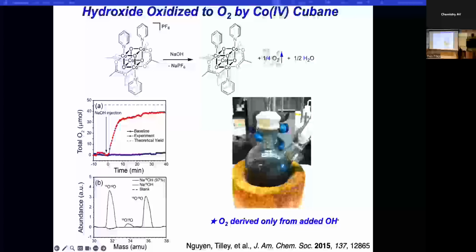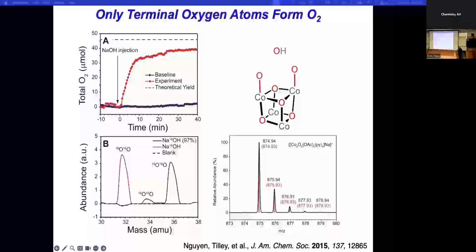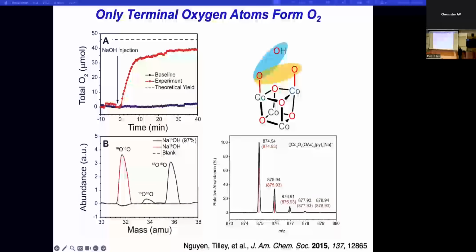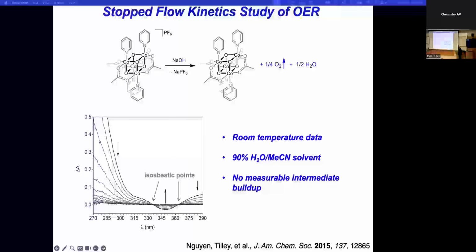Okay, so that means that the catalysis is happening on the surface of that cluster. And if you think back to the 6 different ways I indicated we might form an OO bond, what that meant is that really narrows the choices down to 2. Either an external oxygen is attacking an oxygen species on cobalt on the cluster, or 2 of them on the cluster are combining to make oxygen that way. You can also tell that O18 doesn't get into the cluster by mass spec. And so further analysis is based on kinetics.